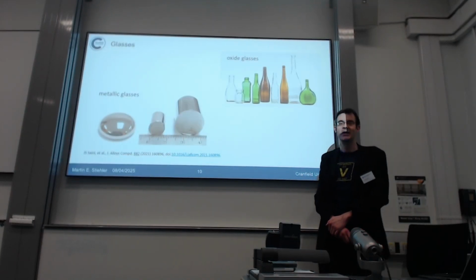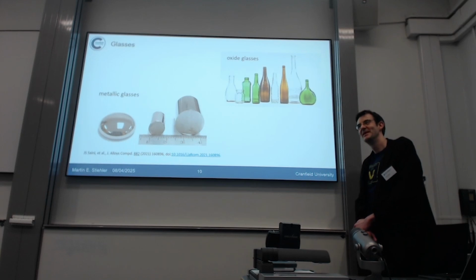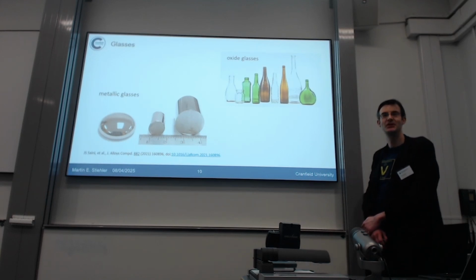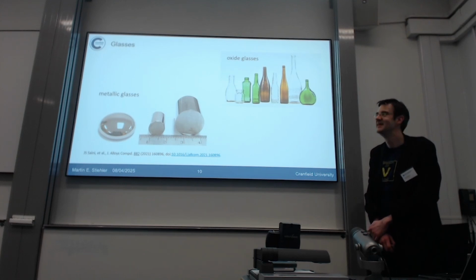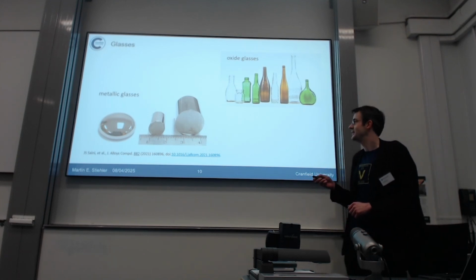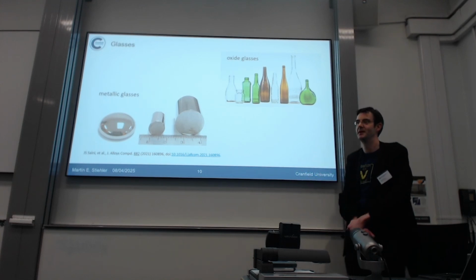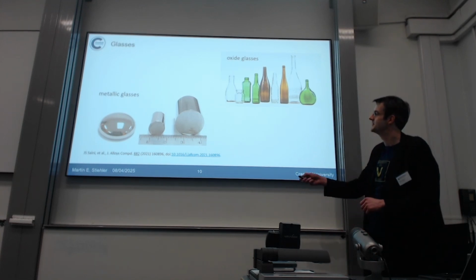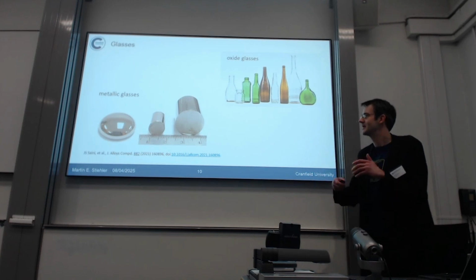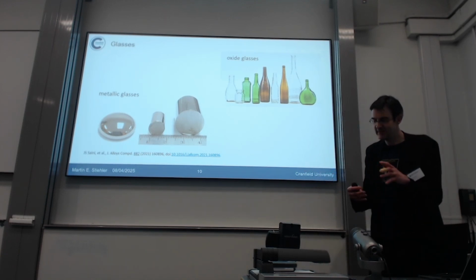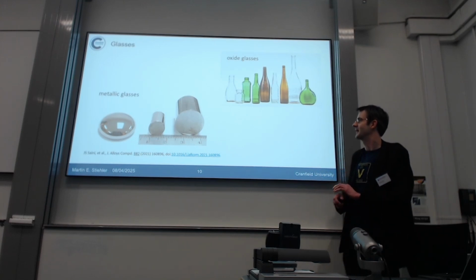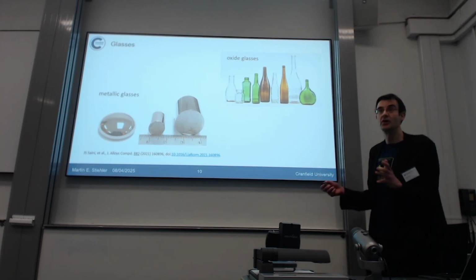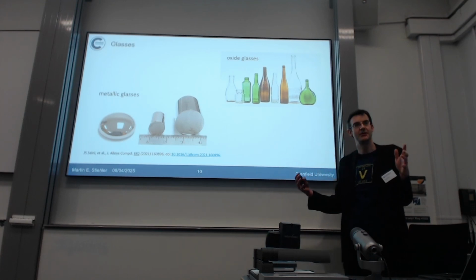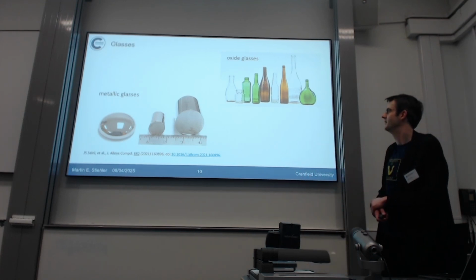And one question that very often comes is, are they transparent? No. Well, transparency has nothing to do with the term glass, right? So metallic glasses from the outside look like metals, but they share the very shiny and smooth surfaces with typical oxide glasses. What you see here comes directly from melting. You put your elements together, you melt them in an arc melter, for example. You mix them properly, they solidify, and they come up with this nice shiny surface, because you don't have grain boundaries that extend to the surface, and that makes the surface very smooth.